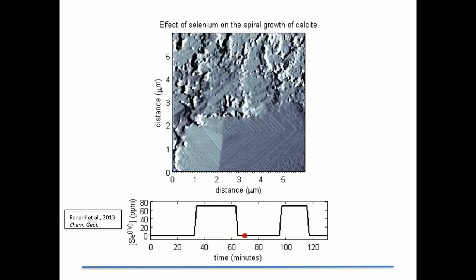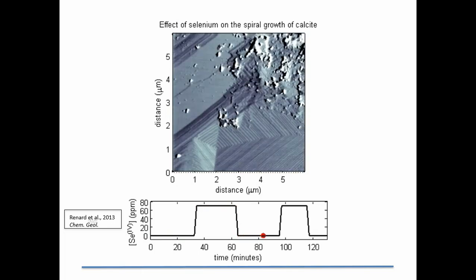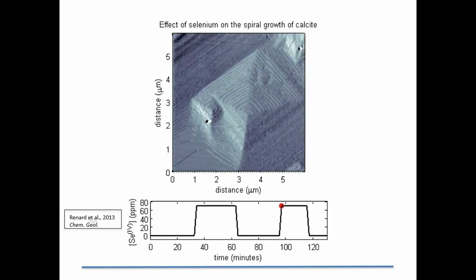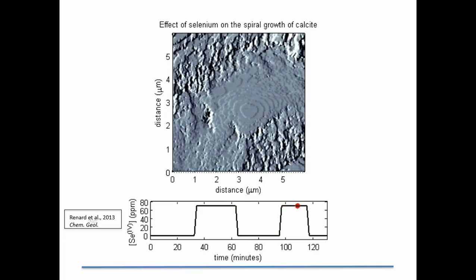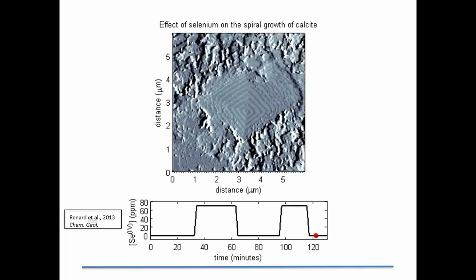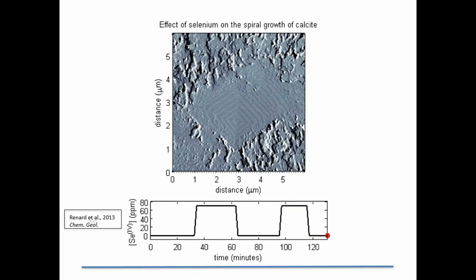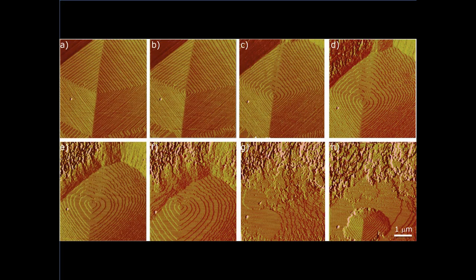We were so excited about seeing the heart, we were neglecting the fact that all of these merged nanoparticles were blocking the surface. When we added the solution, you can see from the bottom, we add the solution, we get the nanoparticles, and we take it away. We add the solution, we get the nanoparticles, and we take it away. And we get the dominant growth from the supersaturated solution with calcite. Okay, I've stopped that film so that you can see the progression from the first growth of the supersaturated solution. On we go until we get to the last image, and we see nanoparticles together with a distorted normal spiral growth. The distortion is most likely because of incorporation of selenium ions in various positions on that pyramid.